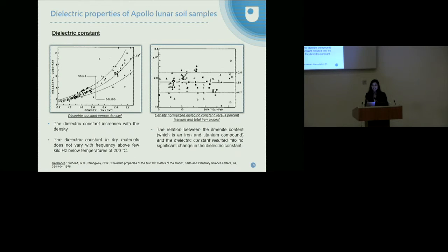density. The dielectric constant is commented to be not varying much with frequency above a few kilohertz below the temperature of 200 degrees Celsius. They did not do much analysis on the chemical composition dependence of the dielectric constant, however, they tried to study the effect of ilmenite content on the dielectric constant, and they found that with the increase in ilmenite content, there is no significant increase in the dielectric constant. But they also commented this does not mean that ilmenite is not having an effect, because increasing the ilmenite definitely increases the density, which in turn increases the dielectric constant.